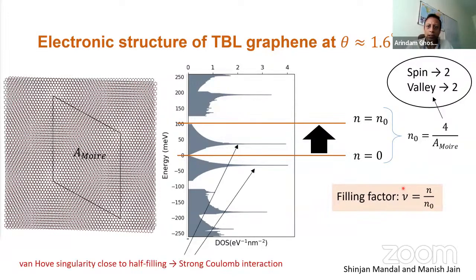So what happens is when you have flat bands, you have very large density of states, and electron-electron interaction becomes really strong when you have the bands roughly around half filling. You can see these van Hove singularities are nearly about half filling, and this is a region where new physics can emerge, and this is what we had probed recently.